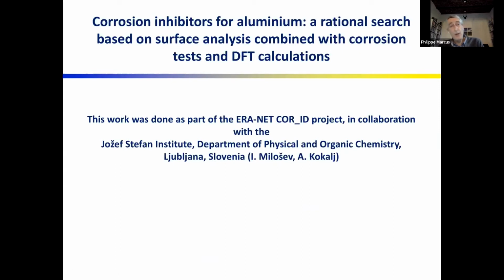Why inhibitors? Well, for obvious reasons, surface oxides are not always protective enough, so in that case, there is a need for surface treatments that can include conversion coatings, but also corrosion inhibitors. So there is a fairly intense activity in my lab, but also in many labs, trying to find new corrosion inhibitors, in particular for aluminum. And I think a rational search must be based on a combination of surface analysis, corrosion test, and DFT calculations.